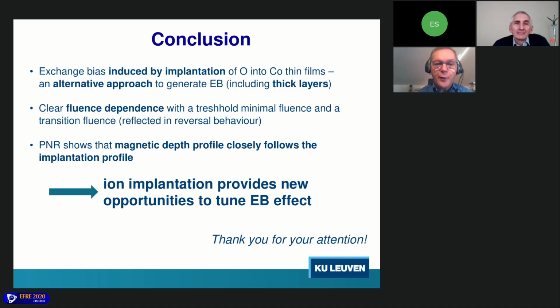And I hope that I've also been able to show that polarized neutron reflectivity, which is in principle a complex technique because you need to go to a reactor source, is also very powerful to really reveal the magnetic depth profile. So the main conclusion is that the ion implantation provides really new opportunities to tune these magnetic effects. I thank you for your attention.